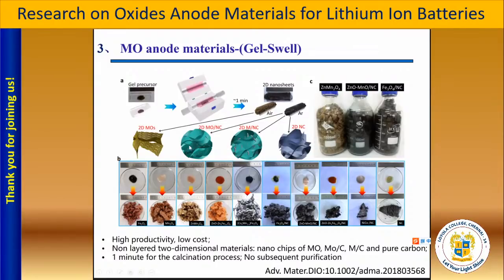The characteristic of this method is that it can fulfill high productivity and is a very cheap way to get, such as, ferroferric oxide, manganese oxide, or double metal oxide, and so on. We can adjust the microstructure with a non-layered two-dimension material, and the time for the preparation process is very short, and it is of high quality.